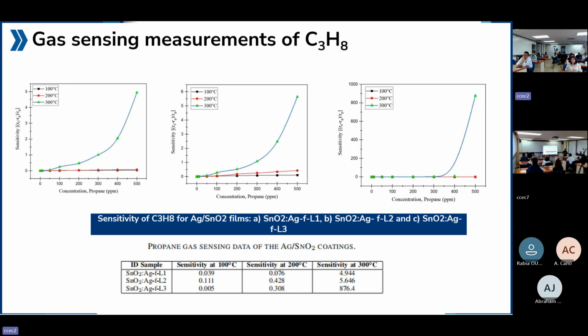Moving on to the measurements of propane. Here, when we talk about propane gas sensing, we see a similar trend to that followed by carbon monoxide for the films. This also depicts that the sensitivity depends on the increase of Ag content and the operating temperature. We can notice that again the 3 immersion Ag added tin oxide coatings showed a markedly maximum response for the gas. At a concentration of 500 ppm and operating temperature of 300 degrees Celsius, the 3-layer immersion of Ag added tin oxide coating showed a maximum sensitivity of 876, which is highly significant when compared to the other two films.